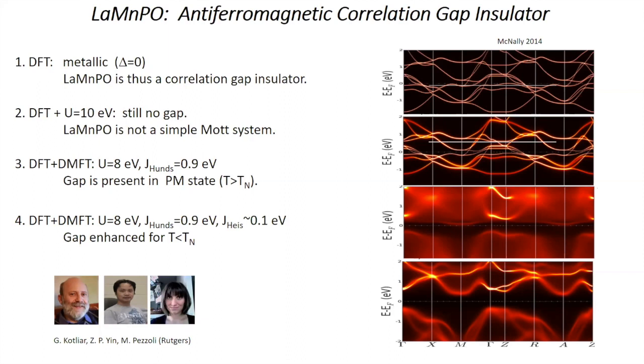And finally, we can get a realistic size gap by adding in a Heisenberg interaction, suggesting that the gap is enhanced in the antiferromagnetic state. So this is the first step of the validation phase, which is we can understand the origin of the gap and we can predict it with reasonable parameters to match up with the experimental value.